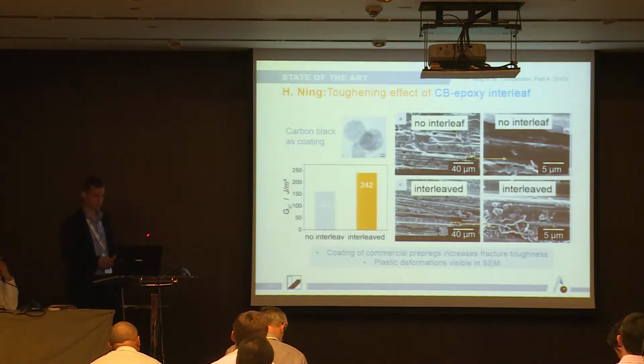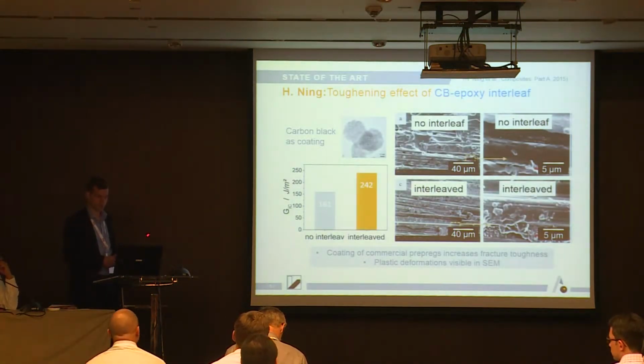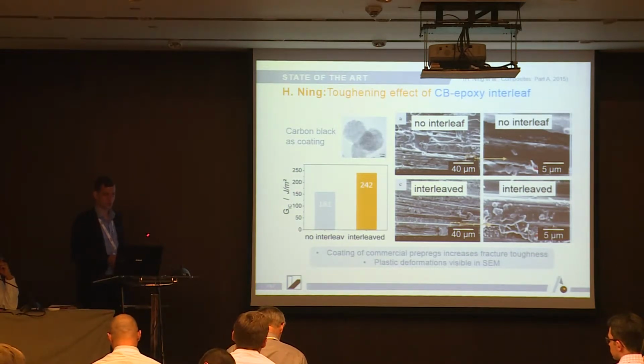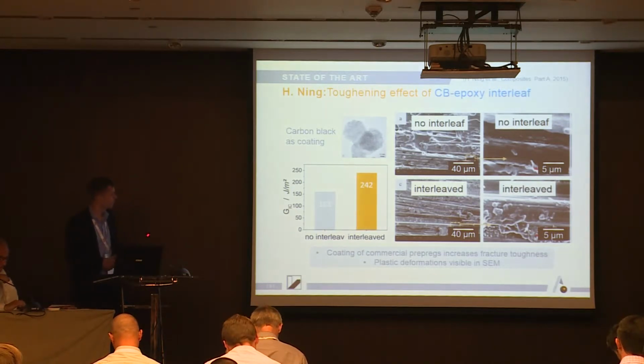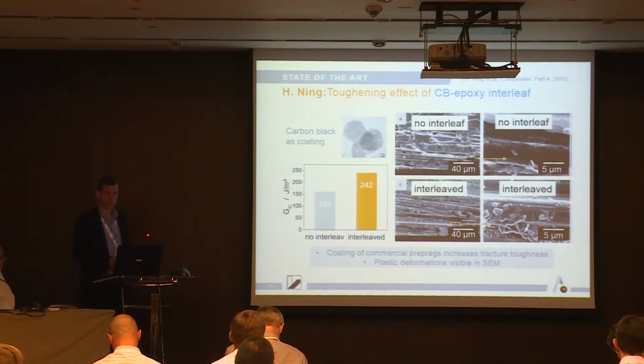So there are different mechanisms to toughen this material. One is to incorporate a filler in the matrix of the material, for example carbon black, which has been used here. You can see that without the interleaf you have a fracture toughness of 161, and with the interleaf 242. And you can see different behavior. This might not be very familiar to most of you, but you can see that there is toughening behavior.